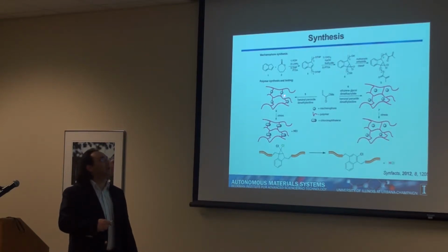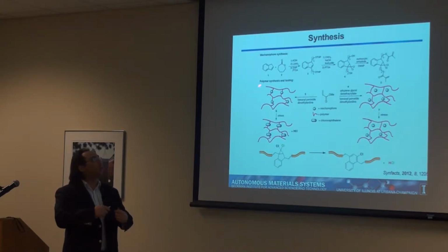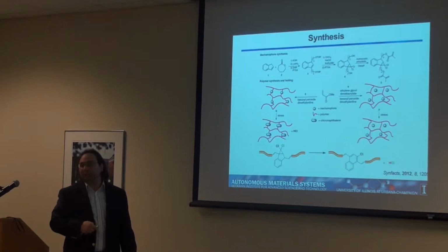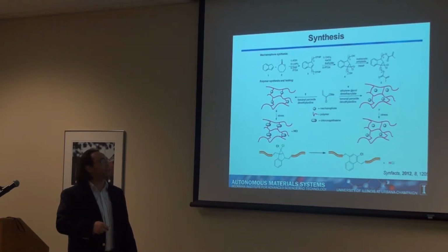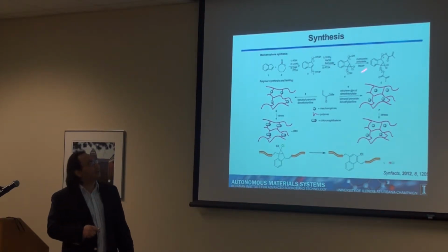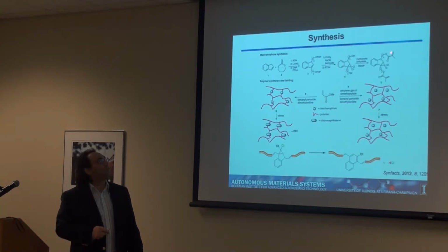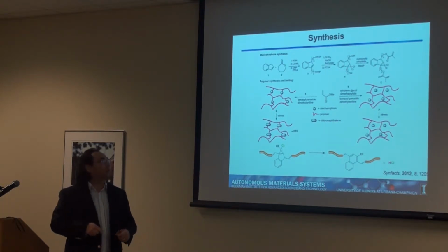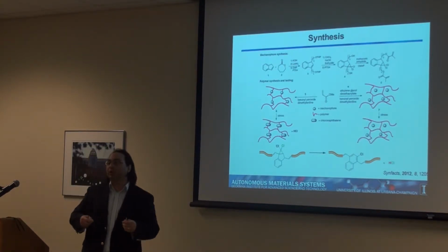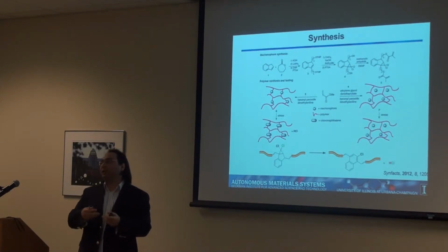And the idea again is that when I apply mechanical force to that, the force will go through the chains, make this chemical reaction, and release acid, 1 acid for each group in this case. For our control, I take the same molecule and I don't put the methacrylate groups, and I just polymerize using a different cross-linker, get the same kind of architecture, but this time, this group is not part of the polymer. It's just a small molecule inside the polymer matrix.